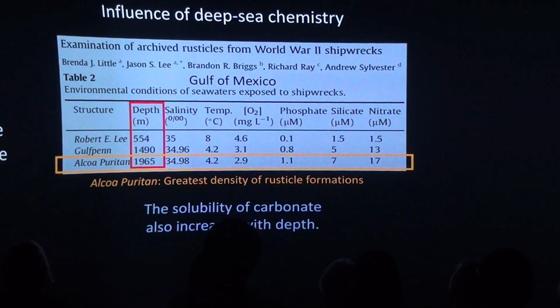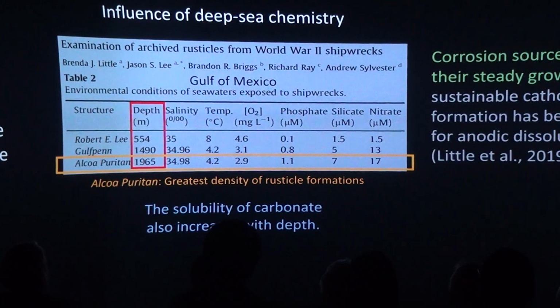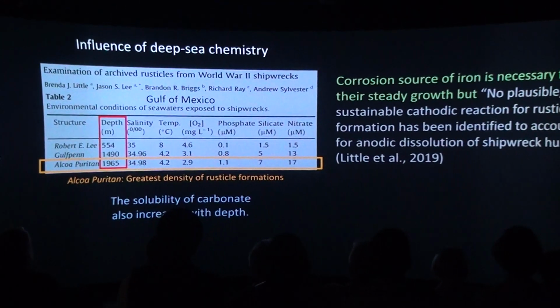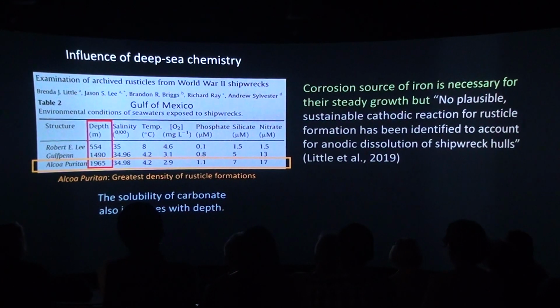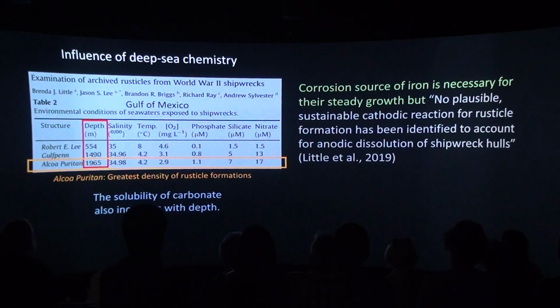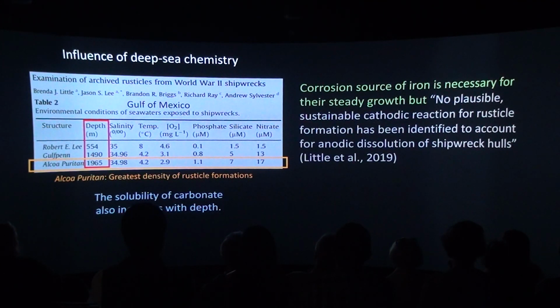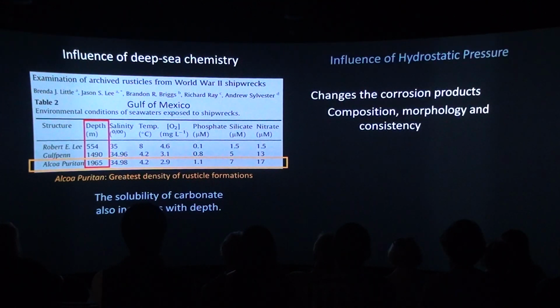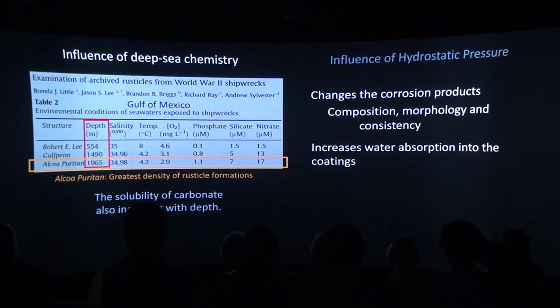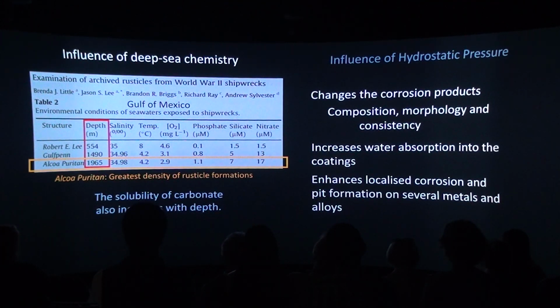The solubility of carbonate also increases with depth, but what they were looking at in previous studies was the corrosion source of iron necessary for their steady growth. But at that time, no plausible sustainable cathodic reaction for rusticle formation had been identified that takes into account the dissolution of metal from the hulls. So that is what we are trying to find out. There's another influence, hydrostatic pressure, that has a direct impact on the corrosion products and the corrosion process. It can change the corrosion products' composition, morphology, and consistency, increase water absorption into the coatings, and enhance localized corrosion and pit formation on several metals and alloys. So that is what I am taking into account in formulating a new rusticle formation hypothesis.